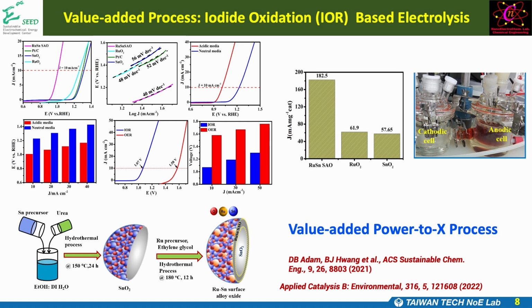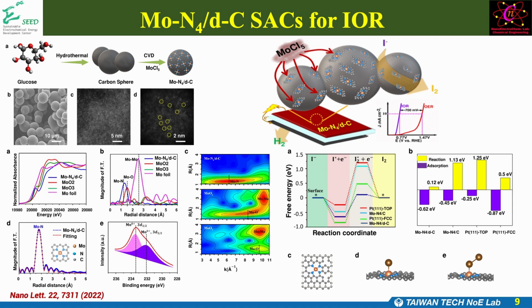So we developed a catalyst. I will just quickly give an example. We actually developed many different catalysts. Like this example, the ruthenium tin alloy oxide. We can use this to reduce the overpotential dramatically. If you compare with the OER base, this potential is operated at 10 milliampere per cm square to produce the same hydrogen, but we need less energy. Oh, too fast. Okay, we also developed this single atom catalyst.